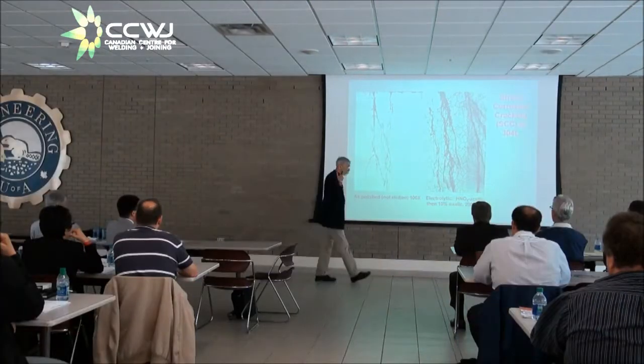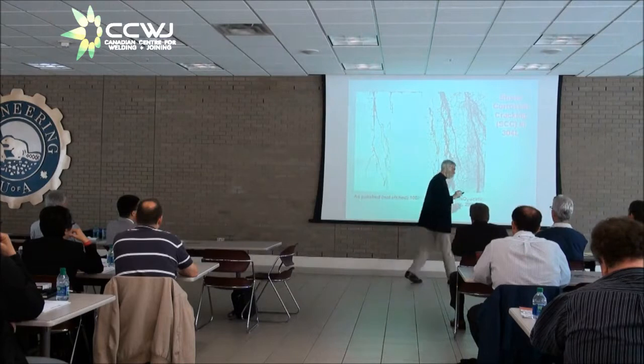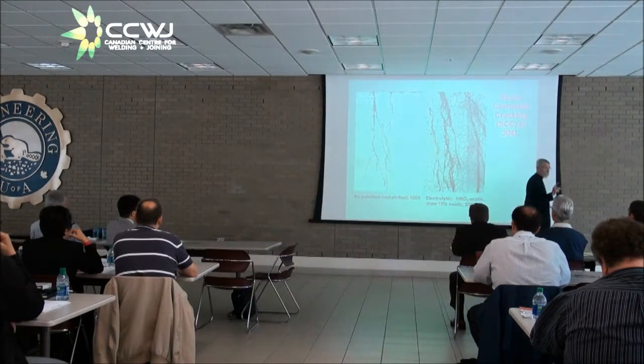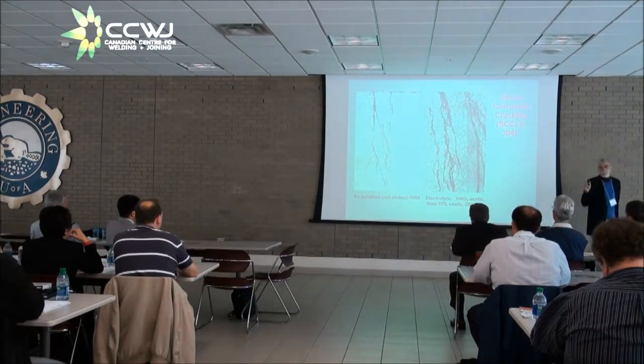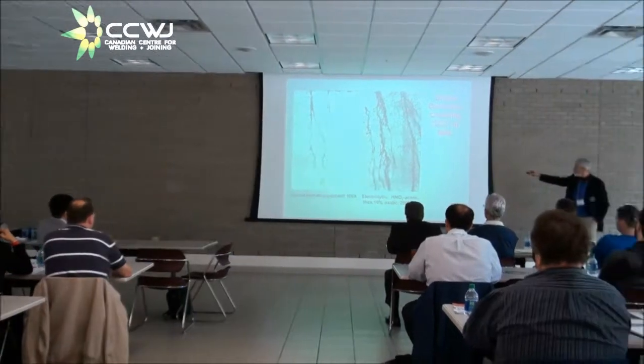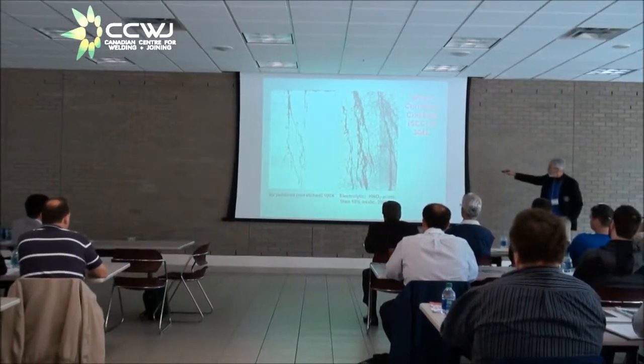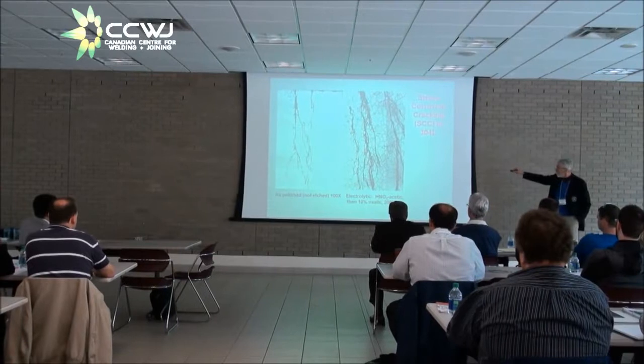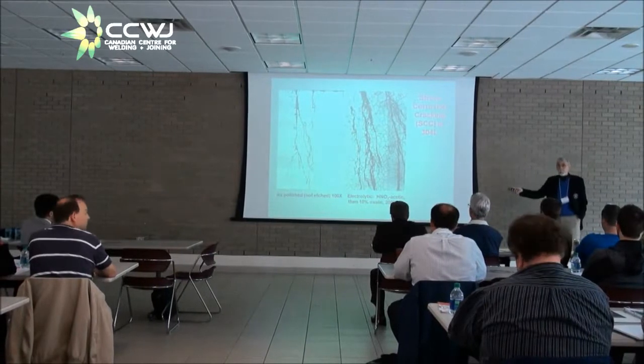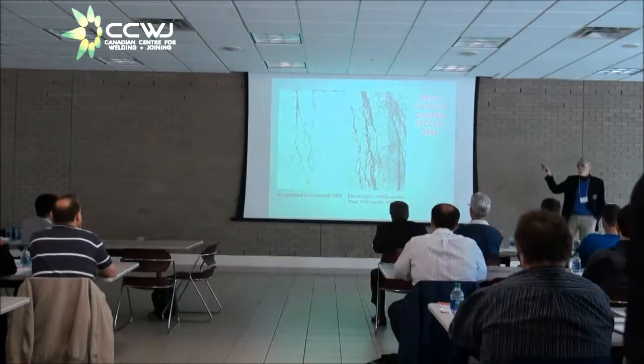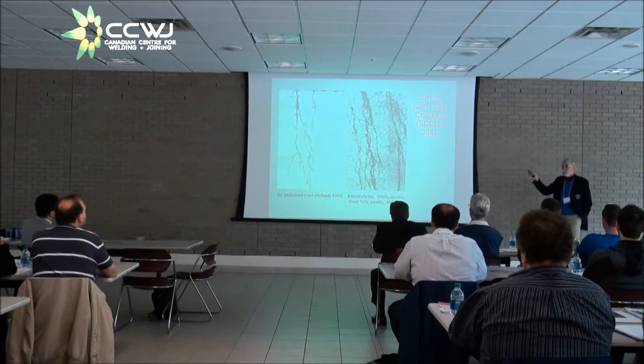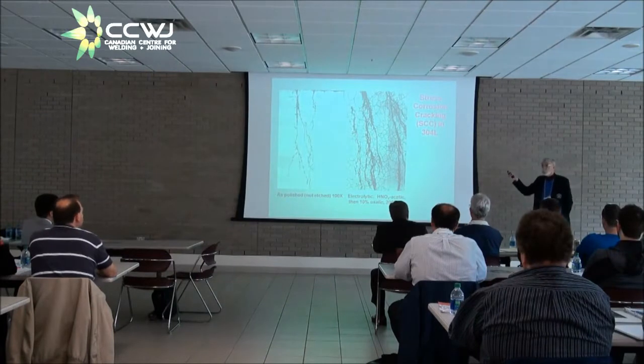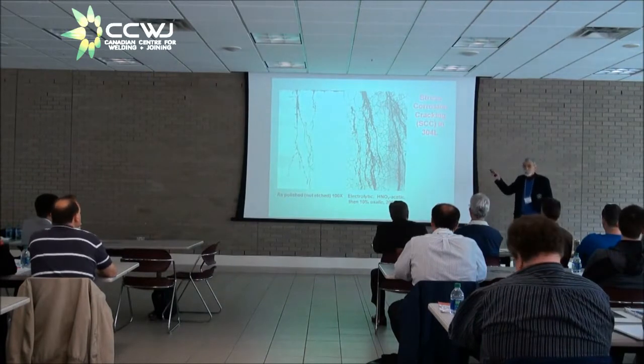And the reason for the etching is to show you that the chloride stress corrosion crack doesn't care about grain boundaries. You can see here, you have grain boundaries, and you have a crack going right through a grain. It jumps from grain to grain to grain. It doesn't care about grain boundaries. This has nothing to do with sensitization. It has everything to do with chlorides and chloride stress corrosion cracking.